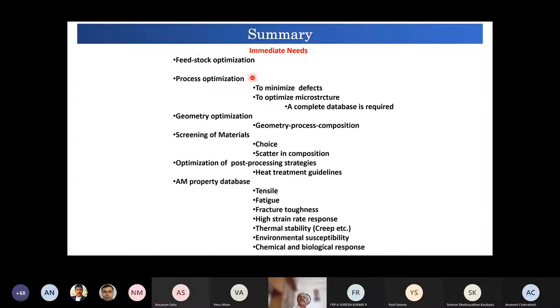One is feedstock optimization. This really requires a deeper scientific understanding of powder metallurgy, because we cannot just go ahead with certifying a 40 micron spherical powder as the criterion. We may get a better performance if we really hit the appropriate distribution and appropriate morphology. So this has to be done. Then process optimization has to be done to minimize the defects. The two diagrams that I have shown, as a function of laser power, as a function of scan speed, all these things have to be done. And such a map has to be created for each material.